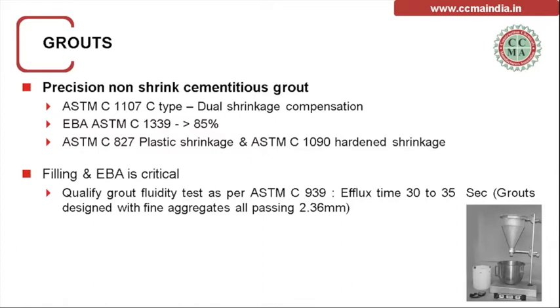So I will just keep my discussion specifically to a couple of properties that are very, very important to deliver the intended outputs of the grouts. It should basically be C-type. C-type means dual shrinkage compensation, that is plastic shrinkage compensation as well as hardened shrinkage compensation. This is the type of grout that should be used. Then the effective bearing area targeted should be greater than 85%, but it is always good to design for 90% when we do the testing, though the standard says greater than 85%.